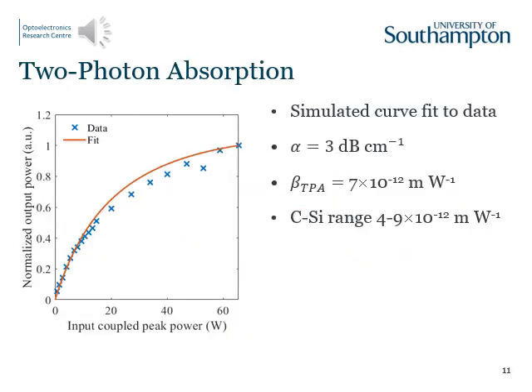2-photon absorption is a third-order nonlinear phenomenon in which the simultaneous absorption of 2 photons excites an electron across the bandgap. The magnitude of this effect is related to the intensity of the electromagnetic field and the material parameter beta TPA, the 2-photon absorption coefficient. As a high beta TPA is detrimental to the performance of a nonlinear device, it is an important variable to characterize. We do this by measuring the output power for a range of inputs with the pulsed laser source and carrying out numerical simulations along the waveguide length.